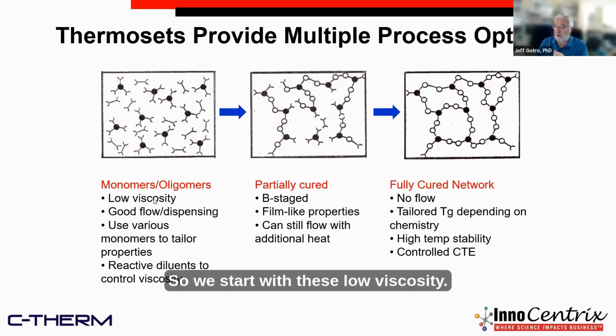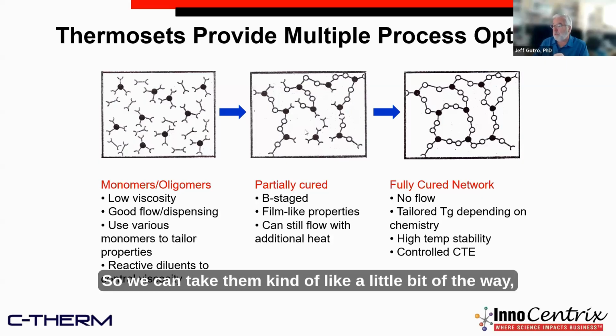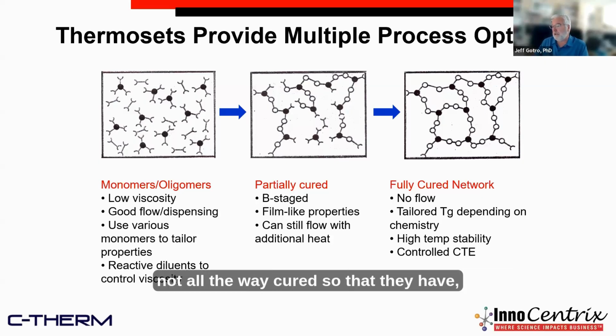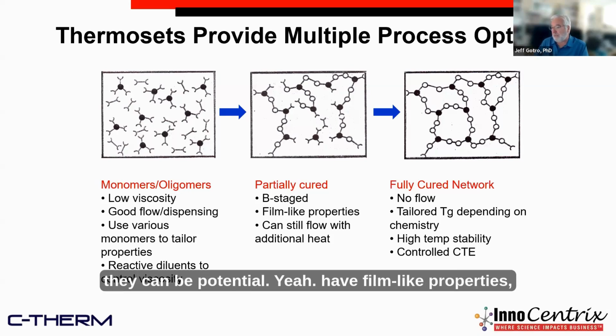We start with these low viscosity monomers and oligomers. We can tailor the properties by the choice of what we put in our initial formulation. We can control the viscosity by putting in diluents, which are low viscosity molecules that react into the growing networks. Then we can partially cure them, kind of a little bit of the way, not all the way cured, so that they can potentially have film-like properties.